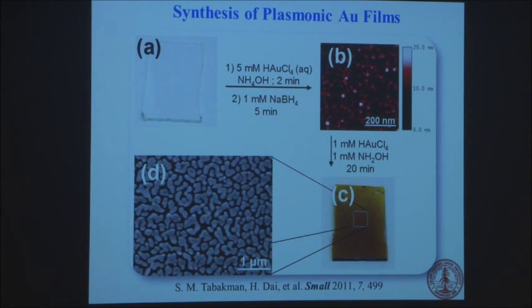So the way we make these films is very simple. It's very much like what you did to develop photographs in the old days. Probably a lot of young students don't know what I'm talking about. But we used to go to the darkroom and put these films into a solution, shake them, and you develop these black and white photographs. So what you're doing is really putting silver particles on that paper to get a picture. Here you're doing very much like that, but you're growing a gold film on the glass. A slide goes in and you pull it out, and you make this gold film. And these gold films, as you notice, are not continuous. They are irregular. They're not even controlled in any way, but we can make them very quickly, very cheaply.